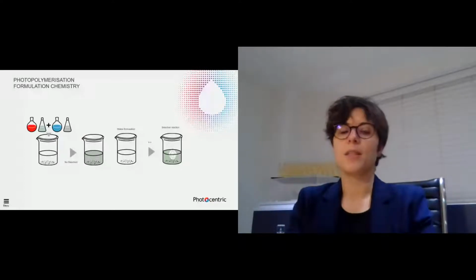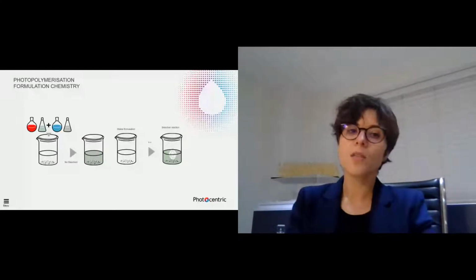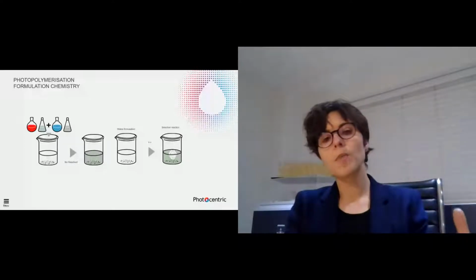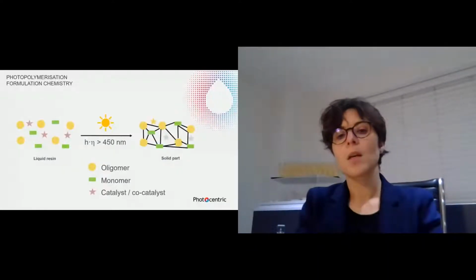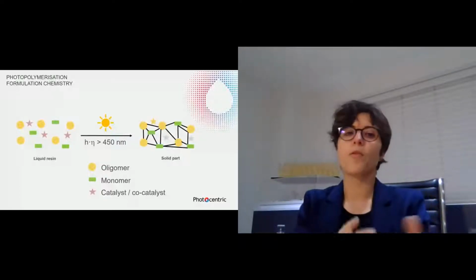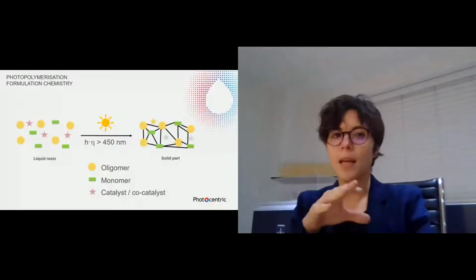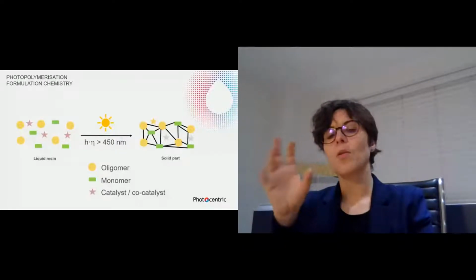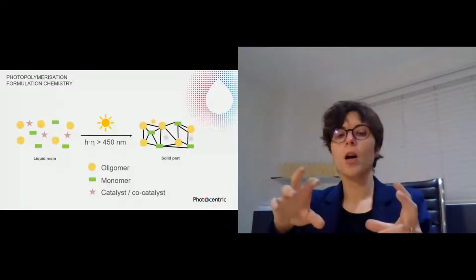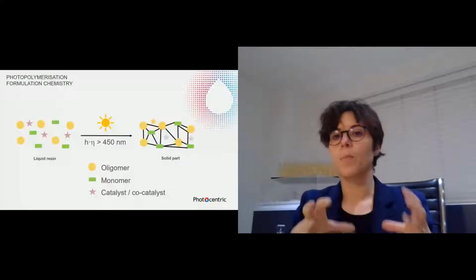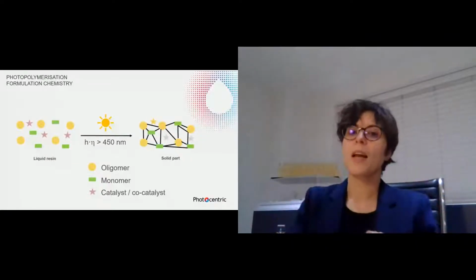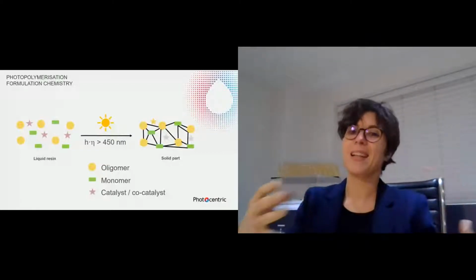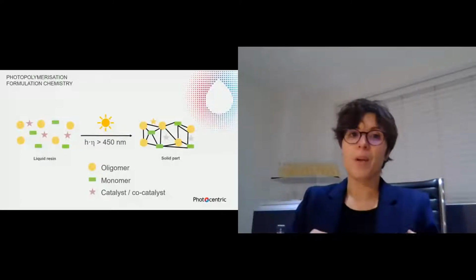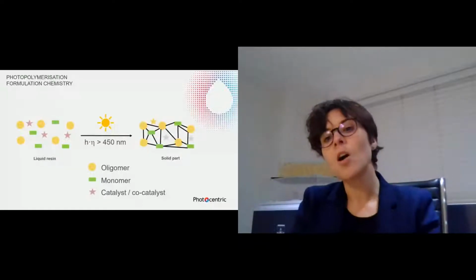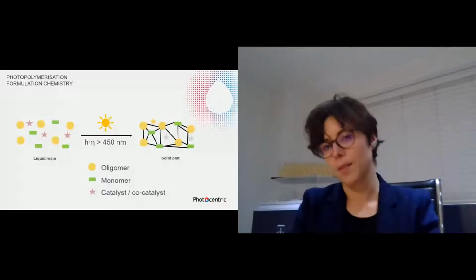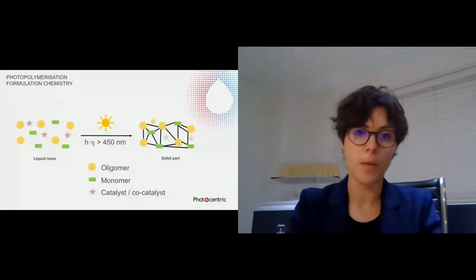And your formulation, which is your liquid photopolymer resin, consists of different components. You usually have an oligomer, which dictates the mechanical properties, monomers, and a catalyst and co-catalyst, which form your photoinitiator system. Whenever you illuminate this liquid resin with light, you create a cross-linking process. So the different monomers and oligomers are cross-linked through chemical bonds. So your parts are very functional and they can resist a lot of environmental conditions, for example, humidity and so on. Also, these parts won't melt. If you heat them, they don't melt. It's a typical thermoset polymer.